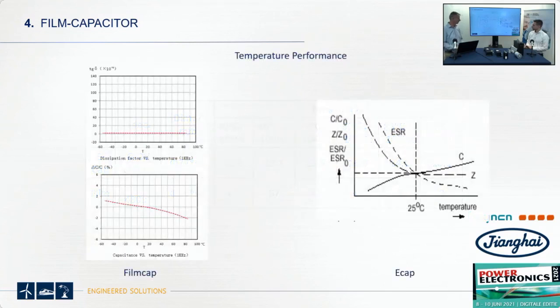Yeah. So further benefits of the film capacitors are the stability at different impacts. Here, the temperature performance: the ECAP changes everything. The capacitance is changed, the ESR changes, the impedance is changed, everything is changed at different temperatures, minus and plus. For film caps, nothing is changed. The capacitance is stable, and the tangent, the dissipation factor, is stable. Nothing is changed. Not at minus temperature, not at high temperatures.